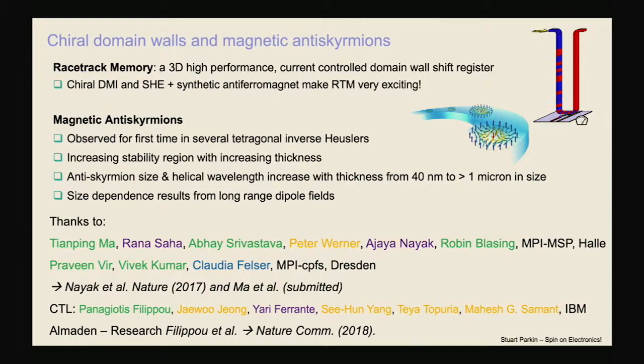So let me just summarize. I'm sorry I ran out of time. Magnetic anti-skyrmions we've observed for the first time, now in more than one tetragonal inverse Heusler, and they have this unique property compared to skyrmions that have traditionally been seen, that their size can be dramatically varied. Very useful, potentially, for technology, simply due to long-range dipole fields.